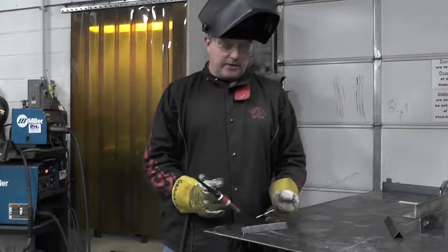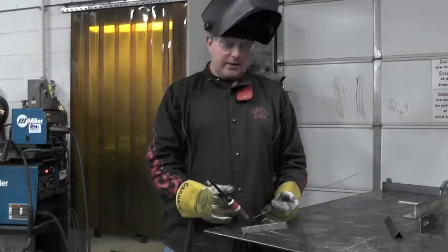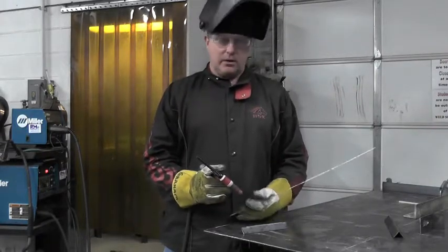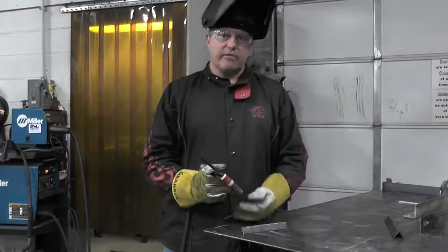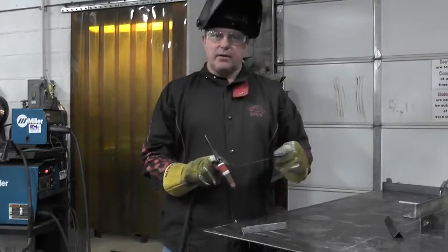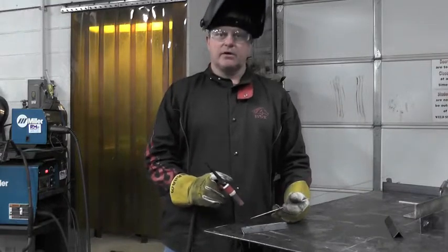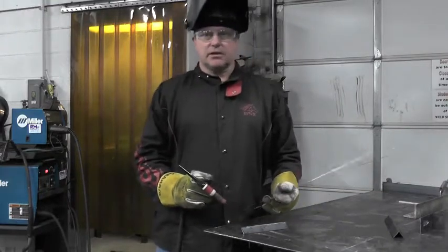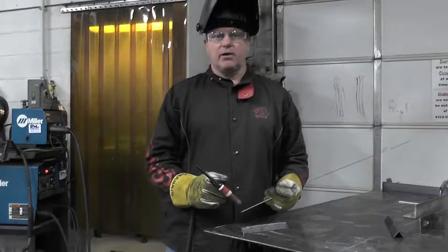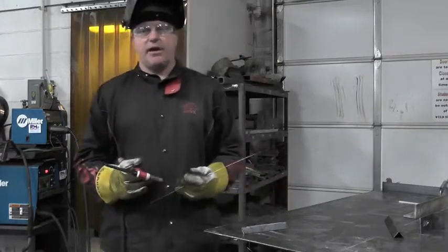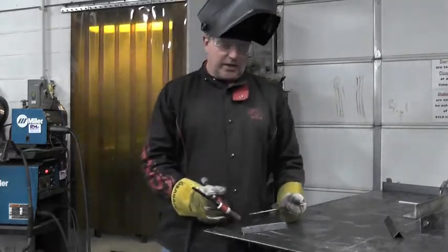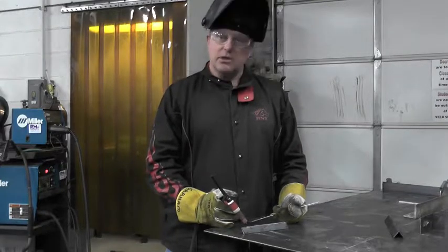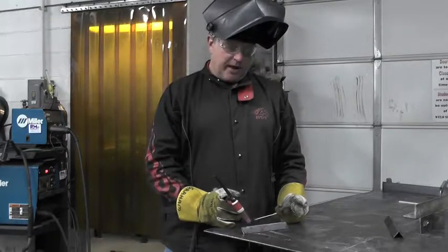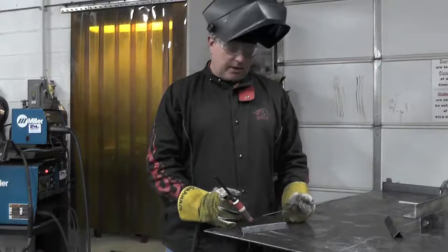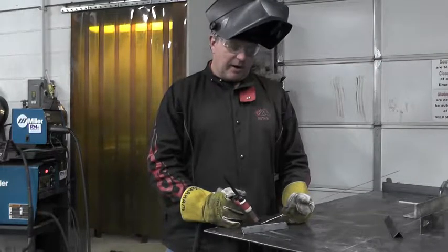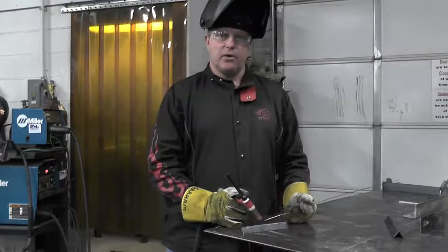The other key component is keeping your filler rod inside the weld zone that the gas is covering, keeping the end of your filler rod in the gas atmosphere. So if you bring it back out, you can get some contamination on it, and then when you go back in the weld, you can actually add some contamination into your weld. So the key is to keep as tight an arc as possible, move down, dip, and keep the filler rod inside of the gas zone as you're doing the welding.